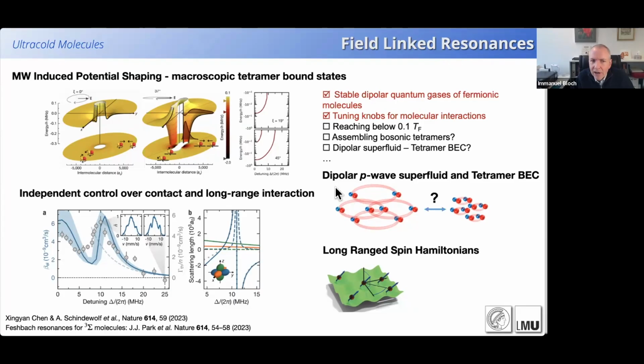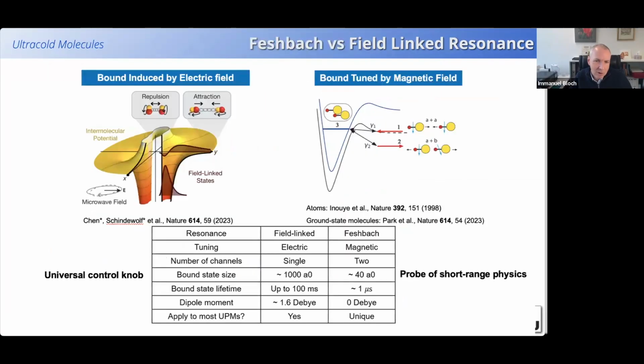I think we're now in a very interesting regime where we have these fermionic molecules that we can bring to low temperatures. We can induce p-wave dipolar interactions between them, and maybe we can hope to get dipolar p-wave superfluids. And if we could do that in 2 dimensions, we'd have topological p-wave superfluids that we can realize in the system. So far, we're not at that point because temperatures are a little bit too high. But if we believe our theory collaborators, that should happen at around 0.2 T/TF. And that's not too far away from where we are in current experiments.